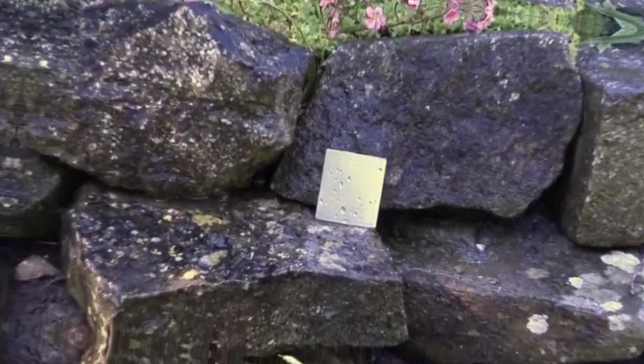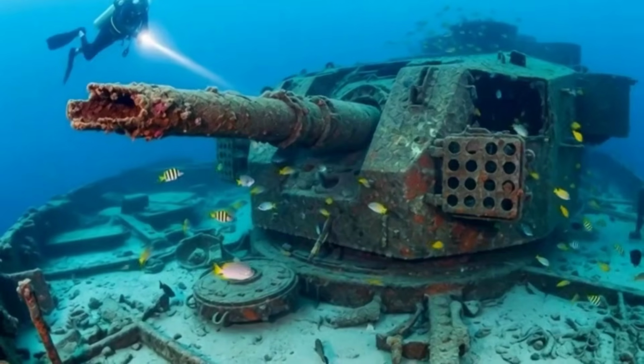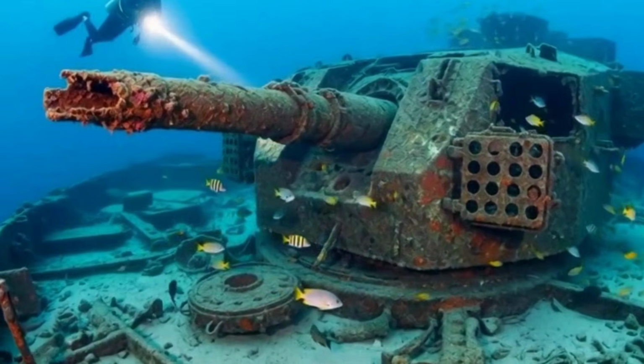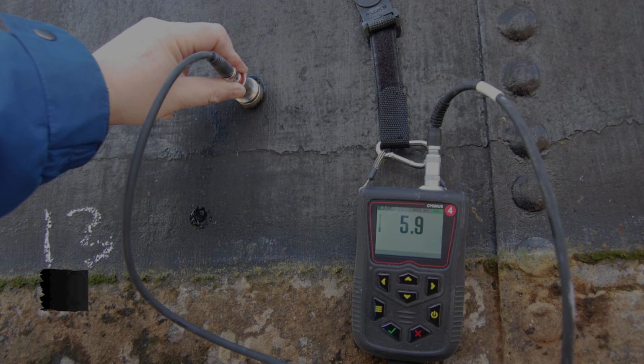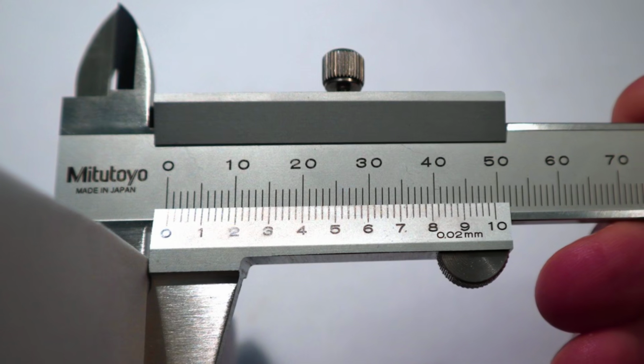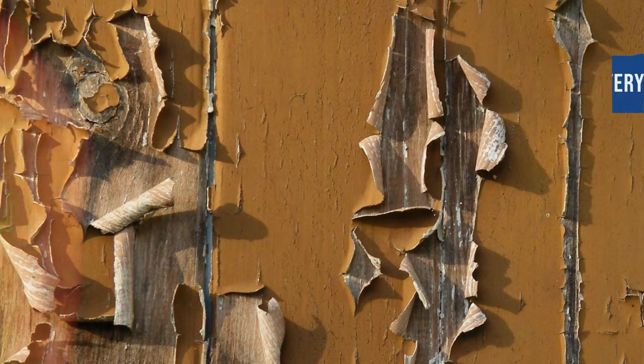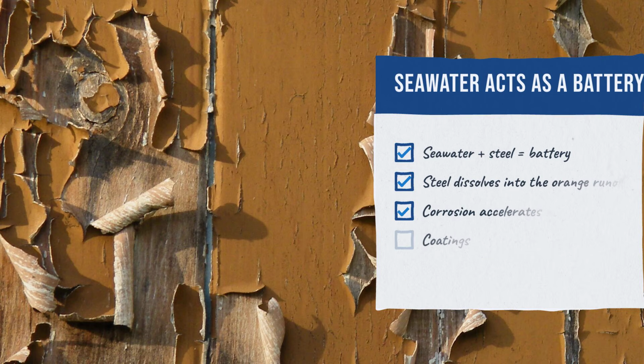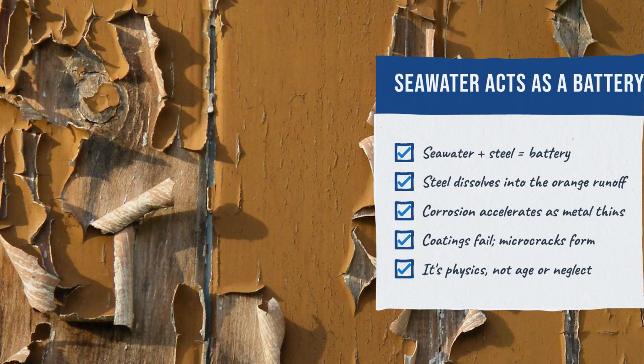And that process is not slow. In open sea water, unprotected steel corrodes at a rate of 0.1 to 0.4 millimeters per year. That doesn't sound like much until you realize a standard cargo ship hull plate is between 14 and 25 millimeters thick, and the rate accelerates as the metal gets thinner, as the protective coatings fail, as micro cracks form.